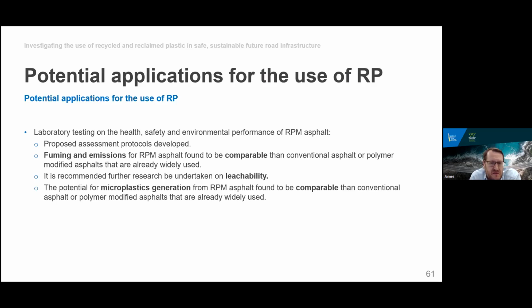It's recommended that further research be undertaken on leachability, and I guess a lot of that is around the fact that there aren't any suitable test methods to understand the potential for leachability of plastics from bound asphalt applications. Most of the leachability tests are more suited to unbound granular materials. So further research might be required here just to check that there aren't any concerns. However, the potential for the generation of microplastics from recycled plastic modified asphalt was again found to be comparable to that from either unmodified asphalt or polymer modified asphalts that are again currently widely used and accepted on our road network.